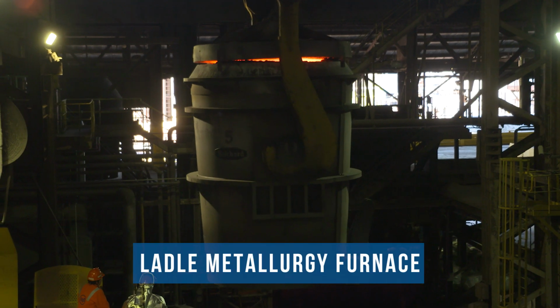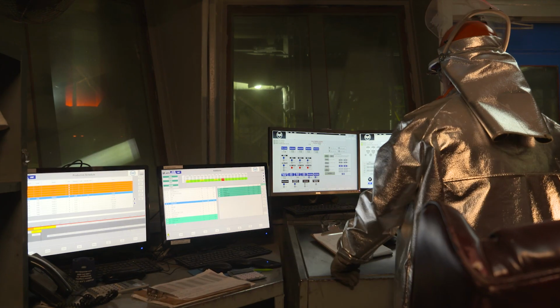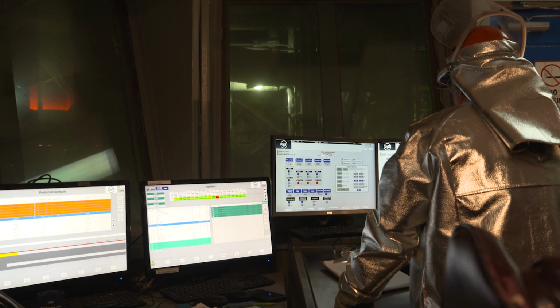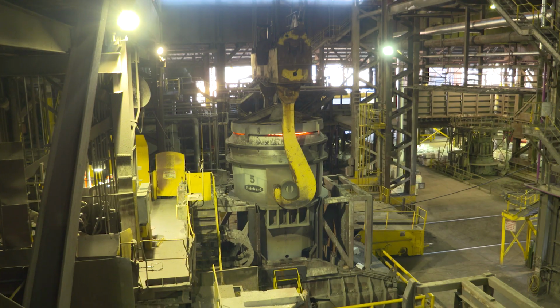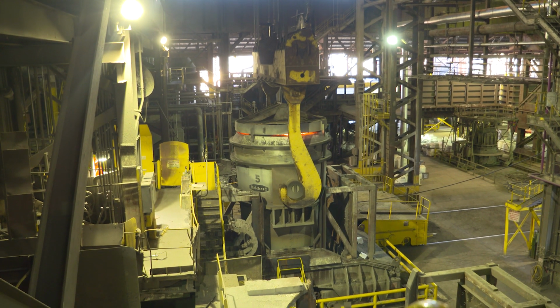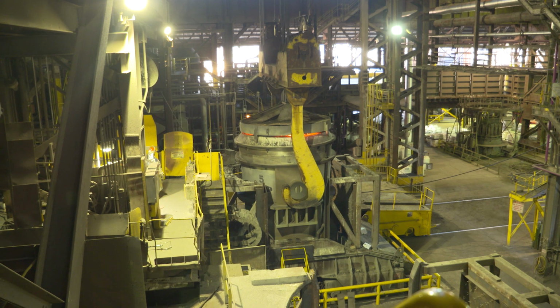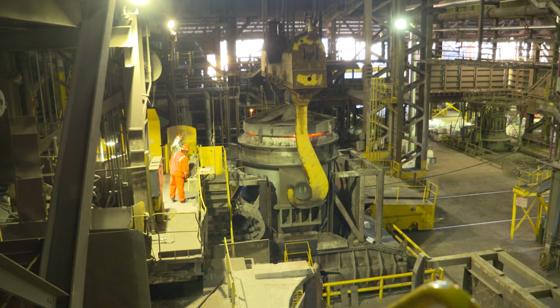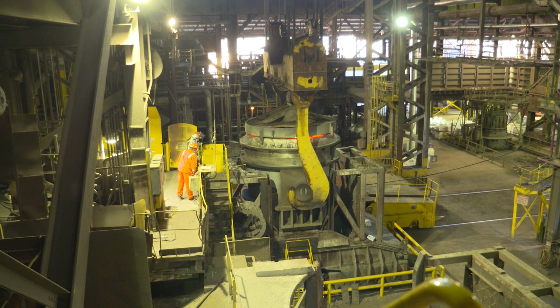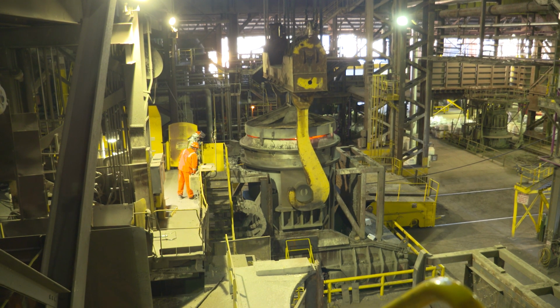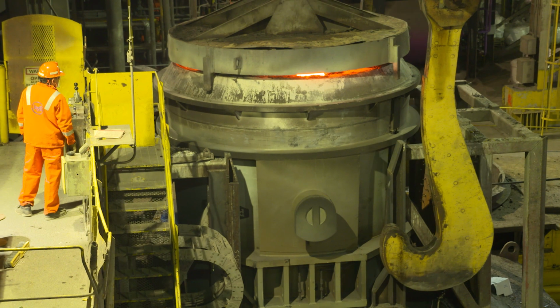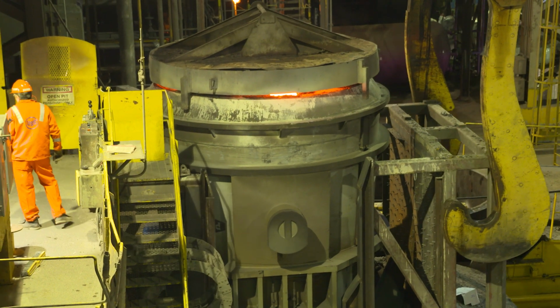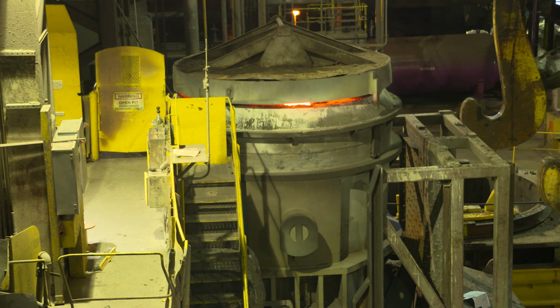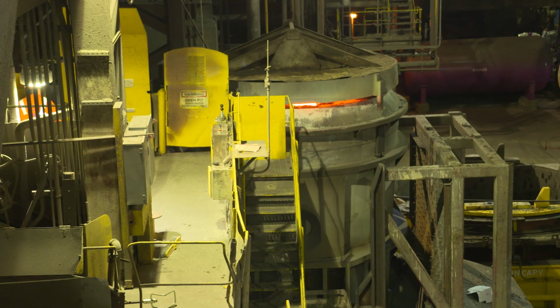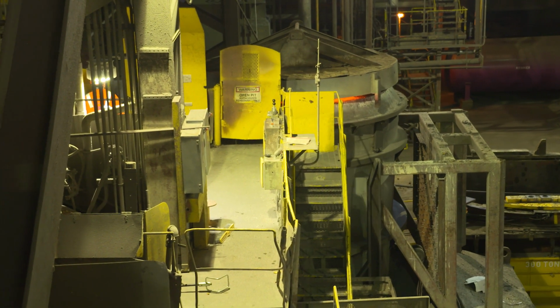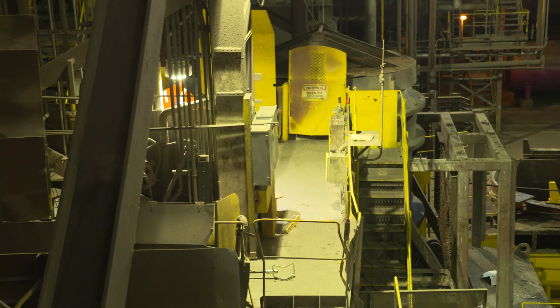The ladle metallurgy furnace, or LMF's function, is to refine the steel chemistry and maintain temperature. It has 3 smaller electrodes that heat the liquid steel while the ladle is being stirred with argon through the bottom of the ladle. The LMF also acts as a buffer or holding area between the melt shop, VTD, and caster. Ladle arrival at the caster must be closely synchronized with the process. This is where the steel is refined into specialty grades while remaining in the ladle. Different alloys are added to the heat in the ladle depending on the grade of steel being made.